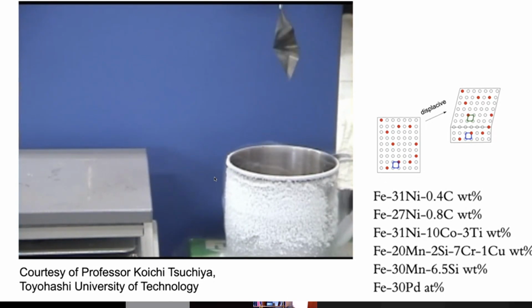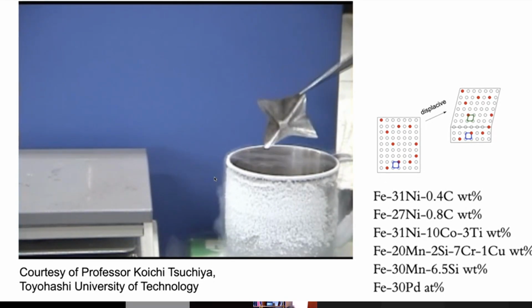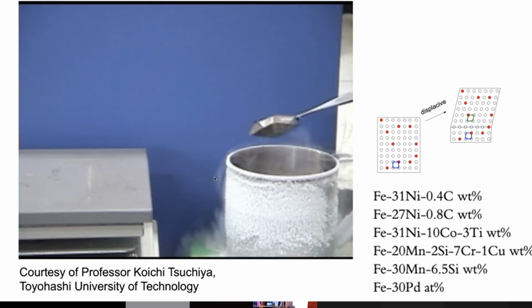And these, of course, are the shape memory alloys. The shape memory effect would not work at all if you created a lot of dislocations during the forward and backward transformations. So the dislocation density is not an intrinsic feature of martensitic transformation. It's caused when there is some plastic relaxation because you're forming martensite at a high temperature where the austenite is quite weak. And of course, this is a single crystal here, okay?